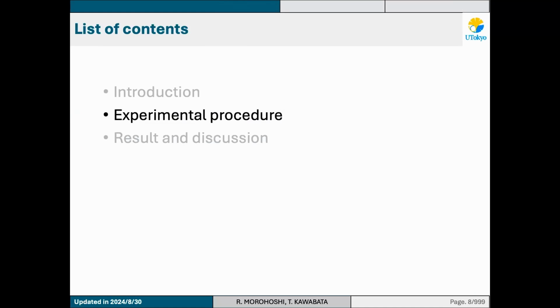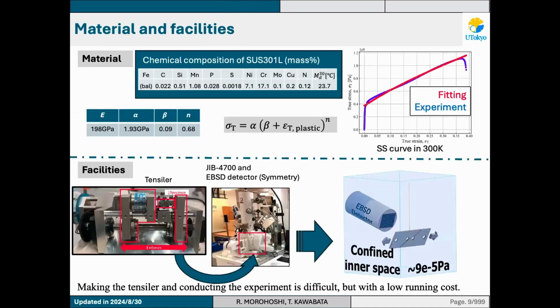And next is about the experimental procedures. This slide is about the material and the facilities. We use 301L austenitic stainless steel because this is a metastable austenitic stainless steel at room temperature. And this is the tensiler. The specimen is set, and the tensiler is set into the SEM, like the schematic images. As you can imagine, making the tensiler and conducting the experiment is pretty complicated, but we can do it with a much lower running cost. So it's obviously a beneficial point.